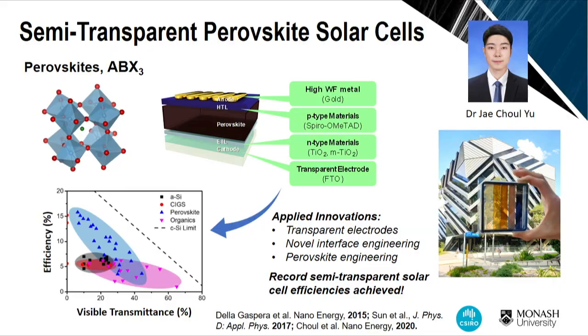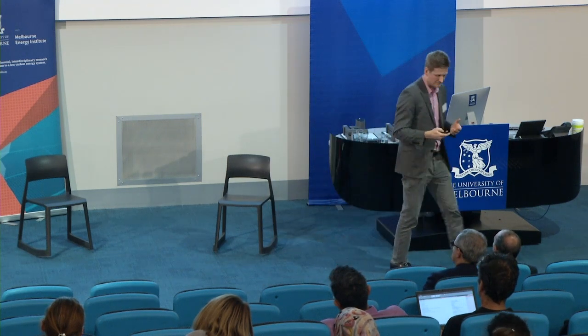And this simple curve, this is efficiency and this is transmittance. It shows you that below 40%, perovskites are just exceptionally good, okay? So this is amorphous silicon, commercial. In fact, this is probably a little bit high. It's of the order of 2 to 3 times higher than amorphous silicon, and that's being conservative, okay? Now, buildings sit here. That's the hot spot, right? About 30% transmittance. So for this technology, we're getting about 10%, okay? That's remarkable. At that efficiency, at that transmittance, amorphous silicon is about 2, okay? So this gives us a tool, and I would say it's a tool to produce energy. It's a technology, right? And these are our tools. These are our production tools.